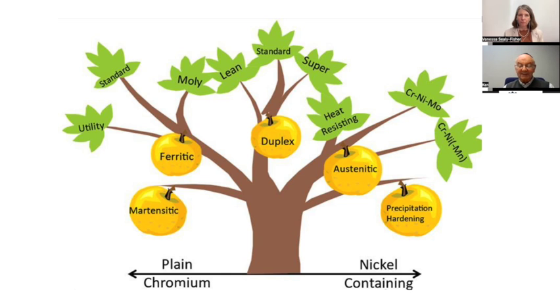But yes, it does mean that there still remains a risk of deleterious, damaging phases forming in the material. And that means the welding operation needs to recognize that you need to balance heat input. That can be done by, amongst other things, managing your welding speed, filler metal selection, diameter, interpass temperatures, etc. And of course, the most appropriate filler metal needs to be chosen from the outset.